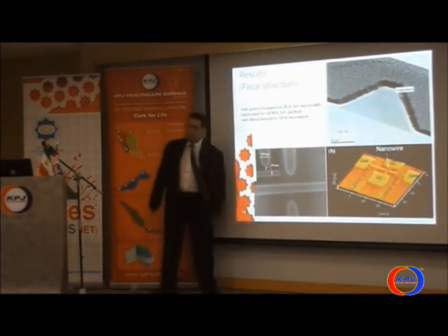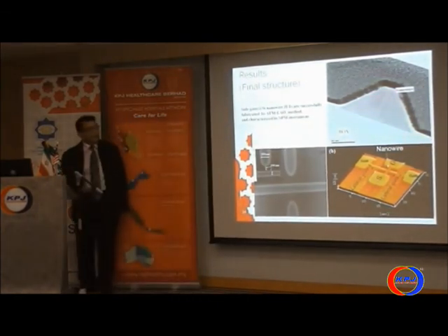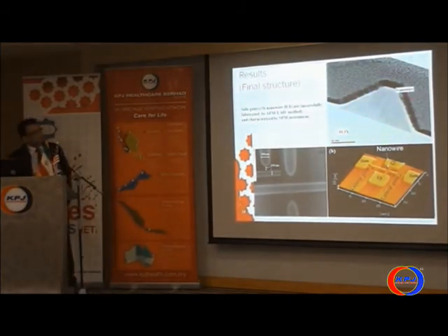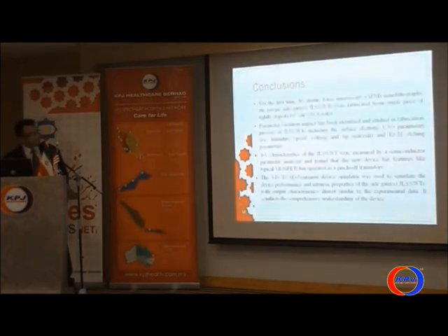The profile of this nanowire, which we cut by high resolution transmission electron microscope. You see that. It's about the size. This is the profile of the silicon. So basically, this one is this. So it's trapezoidal. It's not a square shape. So after the removal of the silicon at the side, this is the profile of the nanowire after the whole etching process. And the current goes through this path between the source and the drain.